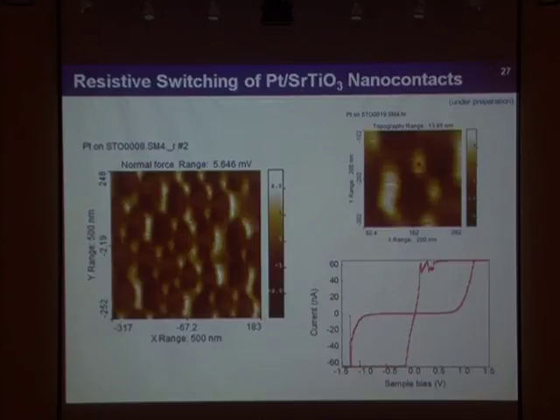The last thing is just a demonstration of how small-sized nanocontacts can work as resistive switching devices. Here we put the electrodes using a nanosphere lithography technique. You may have heard about that. We can put some nanospheres on the sample that will form close-packed structures, and on the exposed area we can deposit electrodes.